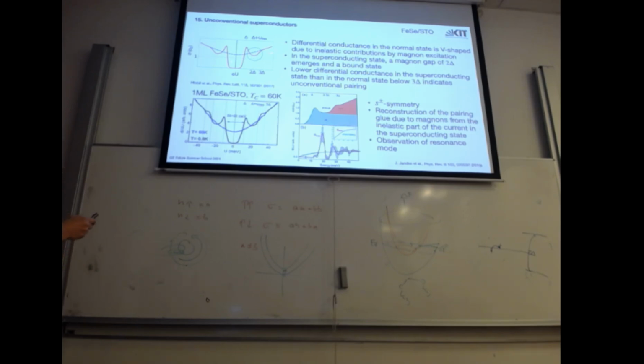So let's say we are in a normal state. We have a normal differential conductivity, an elastic one and an inelastic one, which is the overdamped magnetic excitation. It's very broad. It looks like a V shape if you do the calculation. That's the experiment. It's V shaped, just like in theory. Now we switch on superconductivity. Then we need one delta to enter the single particle density of states, and to do an inelastic process, we will need another 2 delta. So only at 3 delta, I will have the same inelastic current as I had in the normal state. And below 3 delta, my differential conductivity in the superconducting state should be lower than in the normal state, something very unusual.